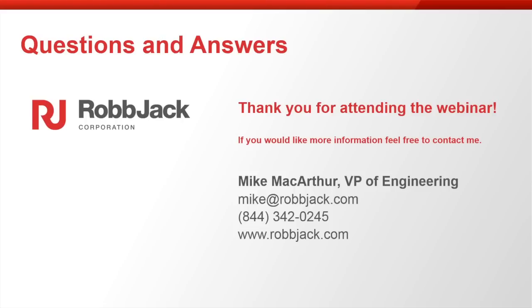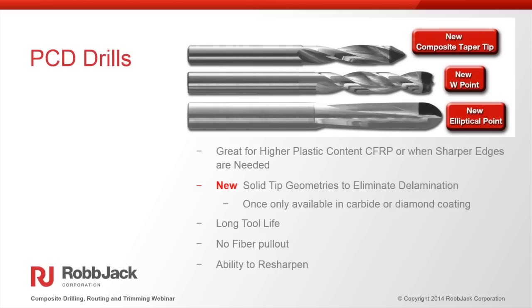Here's another one. Is the diamond tip tool line actually a monocrystalline structure on the tip, or is it polycrystalline? The examples I showed of these tools are not monocrystalline. These are polycrystalline. The difference is, in the past, it's been a very thin disc, and what these are is about a 3 millimeter thick, solid pressed diamond on a carbide disc. So we're actually brazing the carbide to the carbide, and we're not brazing the diamond onto the carbide.